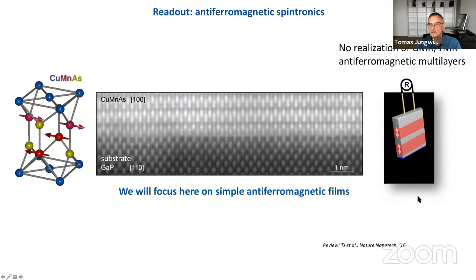In this context, I'd like to emphasize that so far there is no successful realization of these GMR or TMR multilayer structures in antiferromagnets. Obviously, when you think of antiferromagnetic moments, it's clear that realizing these types of devices is much more complicated than in ferromagnets. And indeed, in the entire talk, I will focus on devices which are just made of simple single-layer antiferromagnetic films. Here is an example of a transmission electron microscopy image of a single crystalline epitaxial film of copper manganese arsenide, which is a collinear antiferromagnet, a workhorse material for many of the studies of metallic antiferromagnetic spintronic devices.